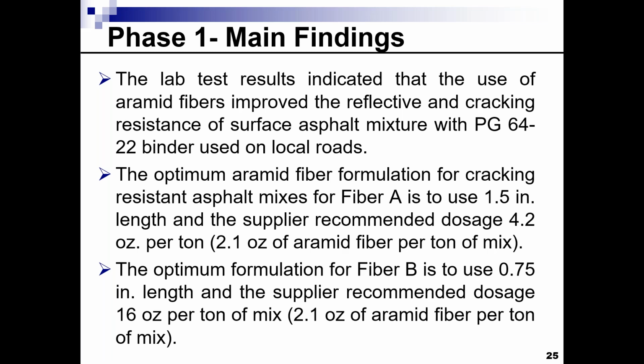The optimum formulation that we have seen for fiber A is to use a long length of 1.5 with the recommended dosage, which is, as I said, 2.1 ounces of aramid fiber per ton of mix. And for fiber B, it seems that the short length, which is the 0.75 inch or 19 millimeter, as well as using the recommended dosage, which includes 2.1 ounces of aramid fiber per ton of mix, will be the optimal. And the recommendation was really to go to phase two so that we can validate and verify the results that we had in the lab study of phase one.